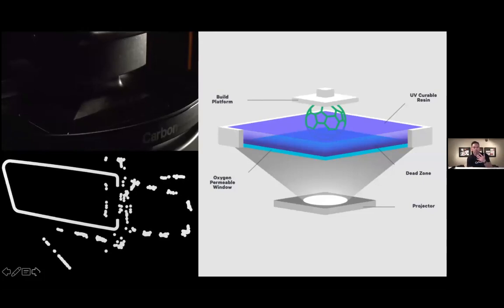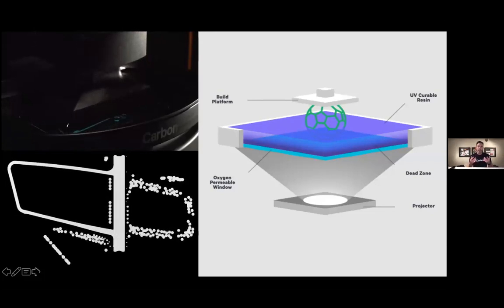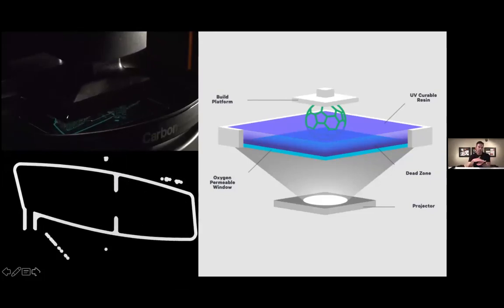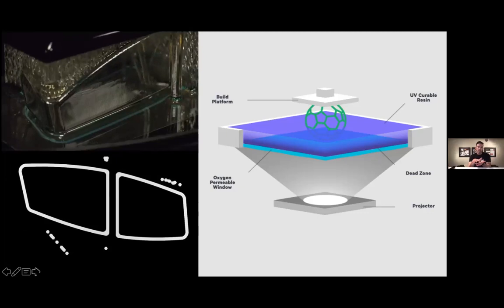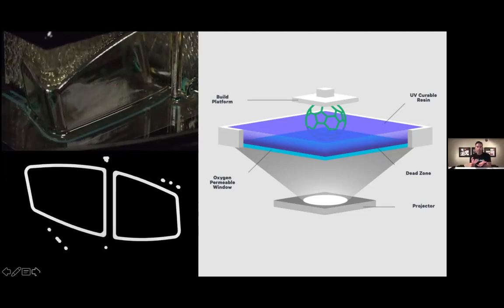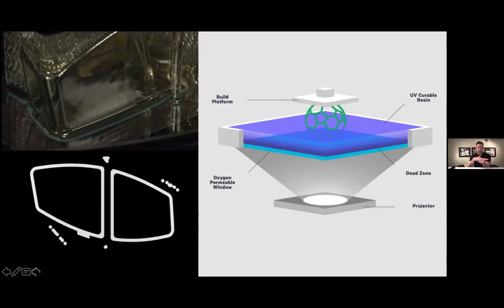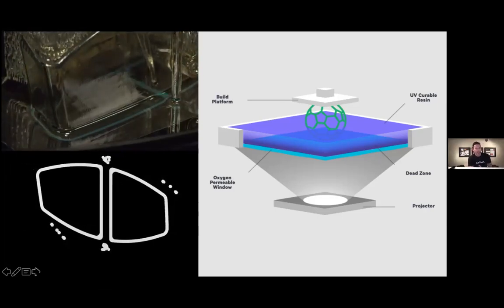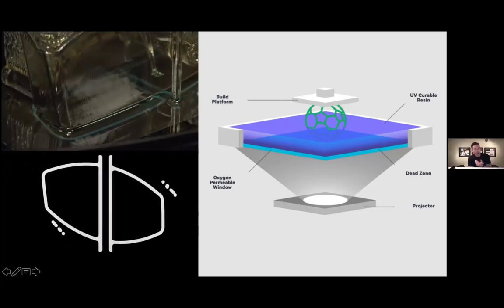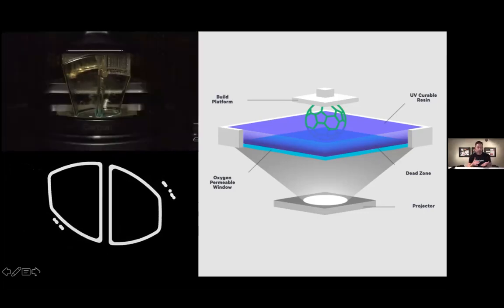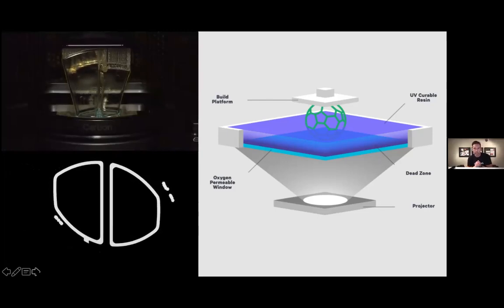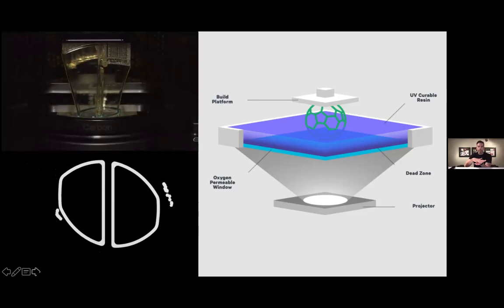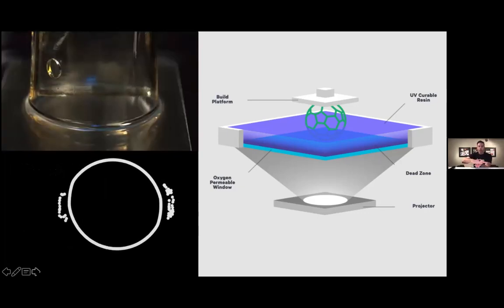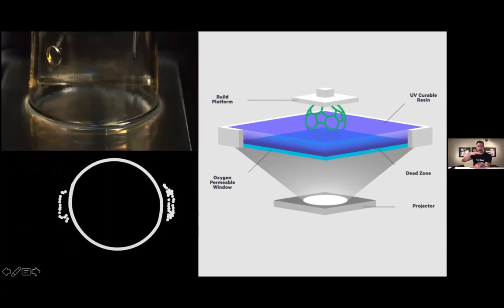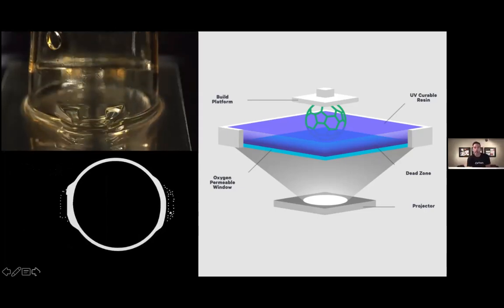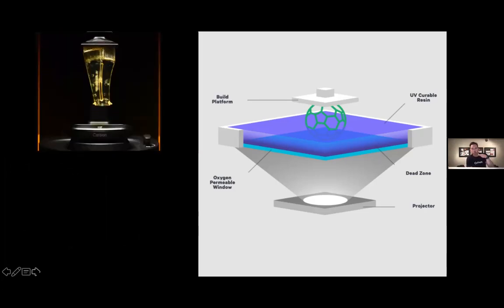So they developed a very special piece of glass. We call it our window, and it's oxygen permeable. It's actually two very special pieces of glass that we pump oxygen between. What happens then is that oxygen can pass through the glass, and it forms what we call a dead zone. I know the dead zone sounds kind of ominous, like what great could happen in the dead zone, but that's where all the magic is, because the dead zone is an area where the resin cannot partially cure to the glass. So although it is partially cured, it will not stick to the glass, meaning the build platform can raise continuously out of the vat as new resin flows underneath, without partially curing each layer and then pulling it off the glass.